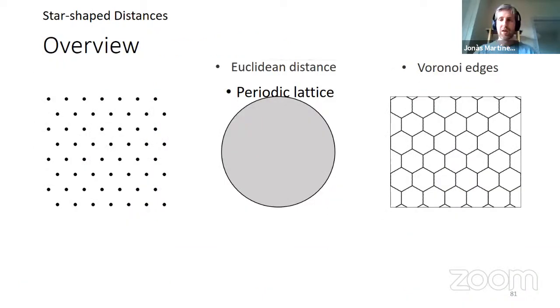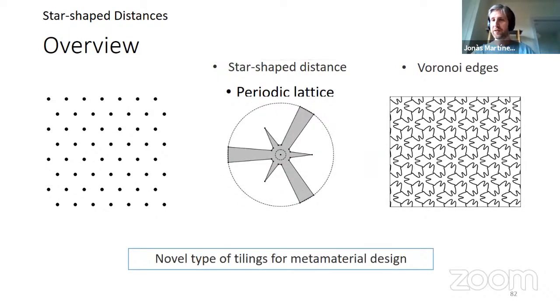So, well, this is mismatch again. Here comes our key idea in this work. Now what we consider is a periodic lattice. And again, with Euclidean distance, if you take the triangular periodic lattice, you get this hexagonal Voronoi tessellation. But we thought of doing something different and changing this distance to another class of distances that we call star-shaped distances. I'm going to talk about this later, but this is a class of distances that can be compactly parameterized by a few parameters and that give interesting mechanical metamaterials. And that's basically the contribution of this work.